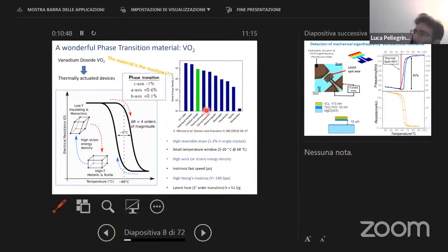You have a lot of energy, which is more than piezoelectric materials and electrostatics, and comparable to, though less than, shape memory alloy, which are the highest-energy actuators that can be used, or the solid-liquid transition. So this material has a lot of energy during this transition. I will show you some examples of what we did later on,